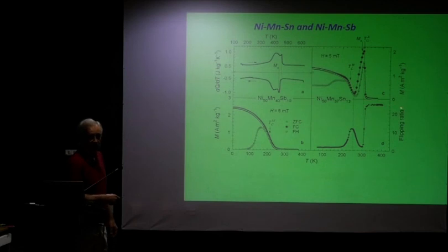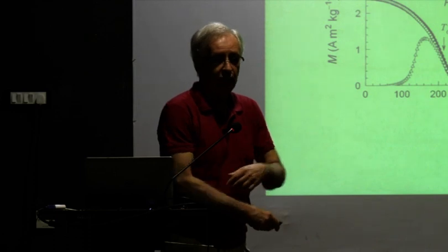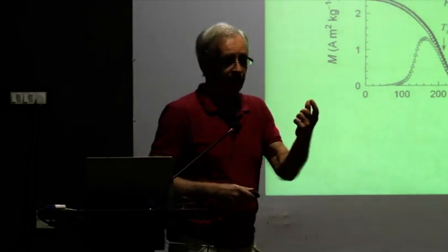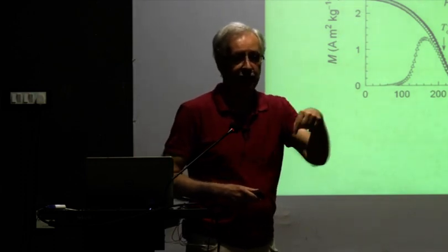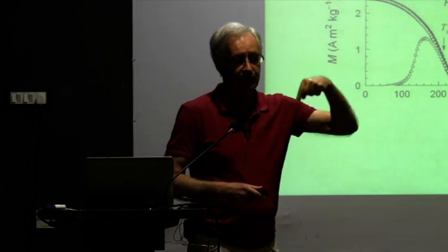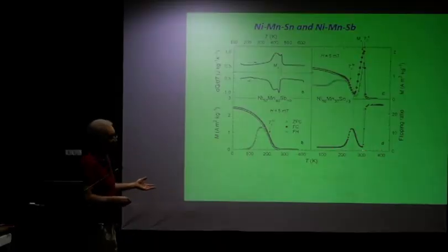So you have a high value of the flipping ratio first, and then as you go down in temperature, when you approach the ferromagnetic state, you have this tremendous drop. And this drop is due to the depolarization of the neutrons caused by the magnetic domains. So the magnetic domains are depolarizing the neutrons in random directions. So the number of spin up and the number of spin down are equal. It's nearly 1. It's at a very low value. Okay? So it's dropped.